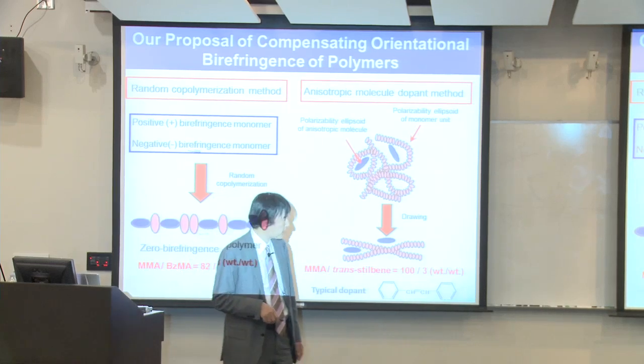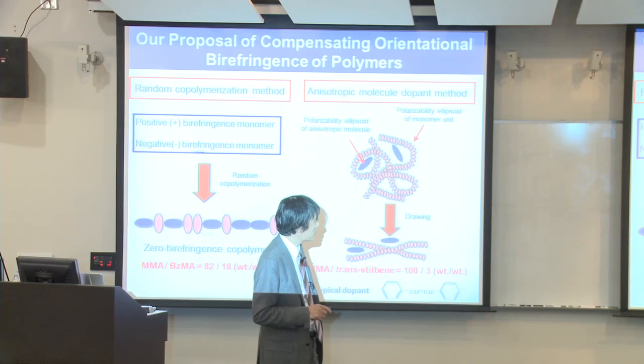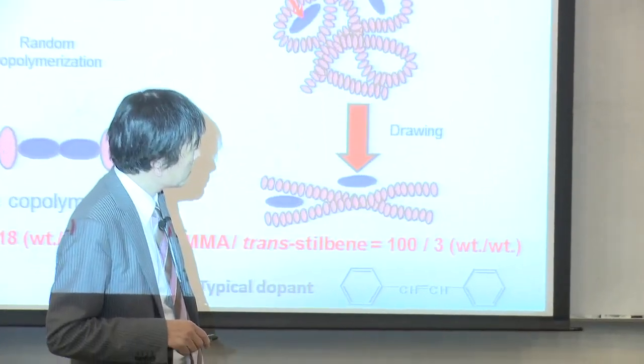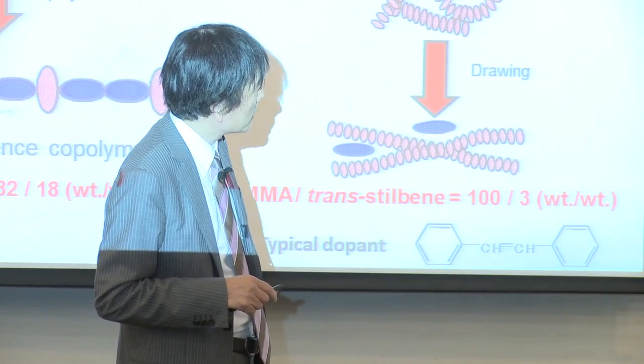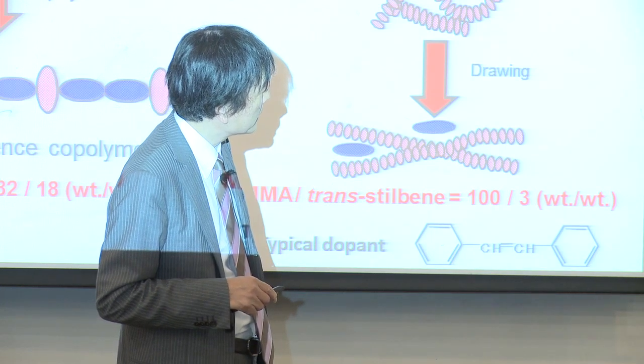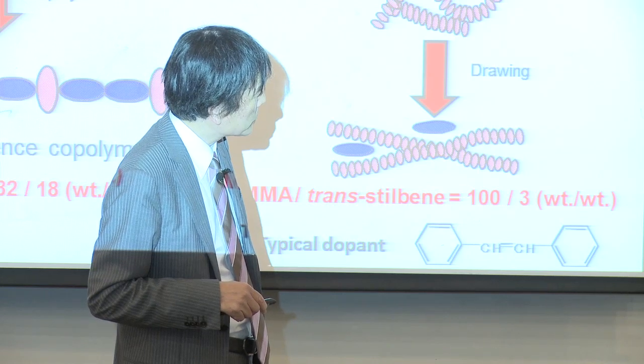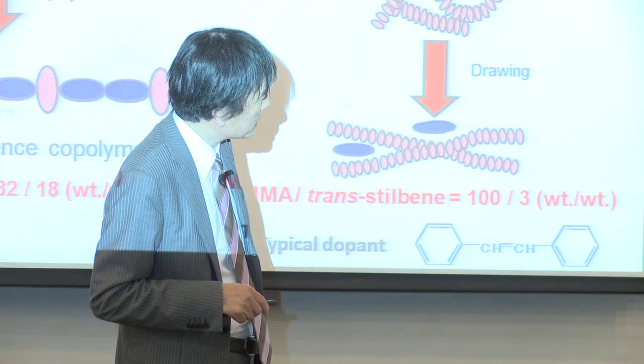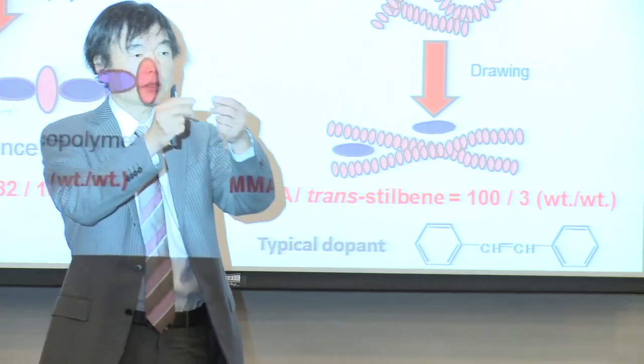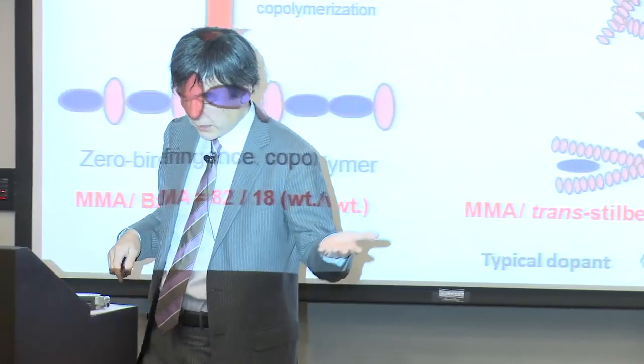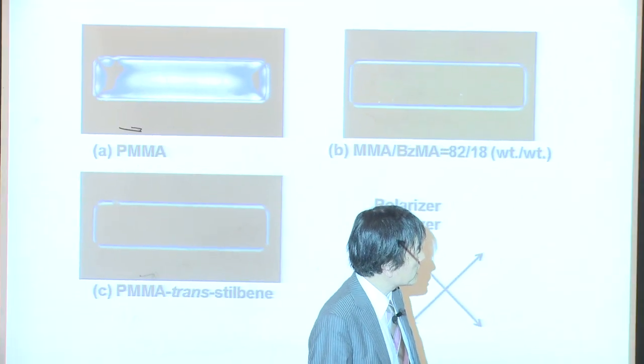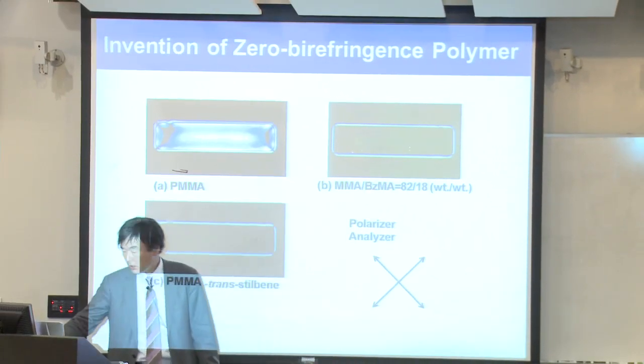So in order to compensate the birefringence, we for the first time proposed the random copolymerization method and an anisotropic molecular dopant method. Even if the polymer is oriented, we do the polymerization with two monomers. One has positive birefringence, the other is negative birefringence, and they are randomly copolymerized, so that the anisotropic polarization is compensated in the size of the monomer unit. So even if the polymer is completely stretched, birefringence is canceled in that area. Adding a dopant that has the opposite sign of birefringence, then when the polymer is oriented, the dopant is also oriented to cancel the birefringence. So with the dopant system and the copolymerization system, we obtain the completely zero birefringence polymer.